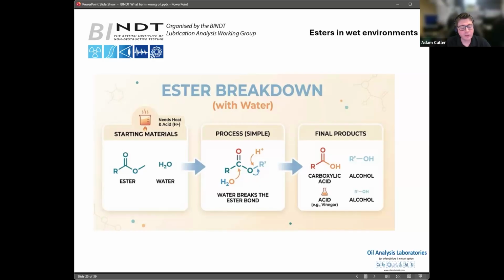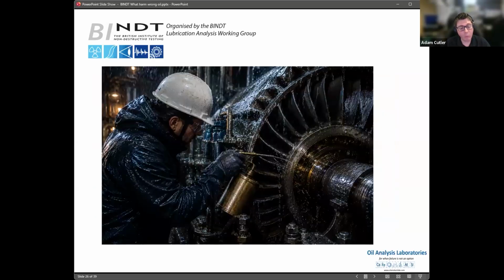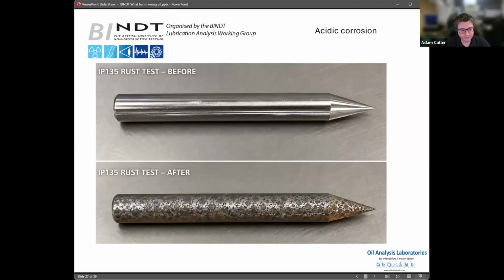And they'll all have rust and antioxidant additives in their additive package, but esters are made from acid plus alcohol equals ester plus water. But we can reverse that reaction. So if we add the water, we can split the ester back into an acid, and that acid can cause corrosion. So in this case here, a wet environment is not the ideal circumstance to use an ester-based lubricant.